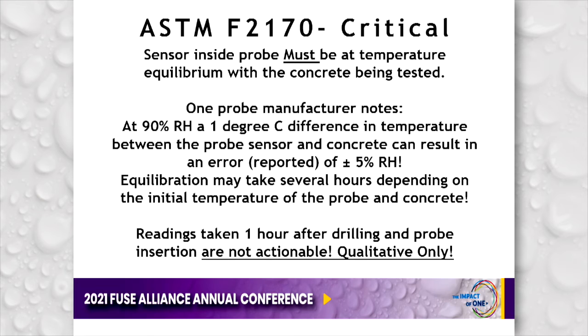One probe manufacturer has noted that at even 90% relative humidity, a 1 degree centigrade difference in temperature between the probe sensor and the concrete can result in a reported error of up to 5% plus or minus relative humidity. So you need to know that equilibration can take several hours, depending on the initial temperature of the probe and the concrete. You know, if you take probes out of a hot car and put them in cold concrete, that's going to be one thing. And conversely, probes out of a cold car into hotter concrete. So it's important, and I know there's at least one manufacturer, now maybe more, saying, oh, you can take a reading an hour after you've drilled the hole and inserted the probe.